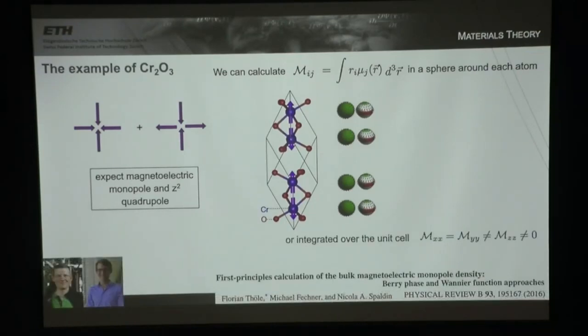We also know how to calculate, it's a bit more complicated, these quantities integrated over the unit cell. This was actually a whole PhD thesis of Florian Thöle. For those of you who work on ferroelectrics, we have all the same problems as in the modern theory of polarization for ferroelectrics, but we know how to do it. And when we do that, we find that indeed we have a Z component of this tensor and in-plane components that are non-zero. And the in-plane components are different from the Z component. So we know what magnetoelectric multipoles we have in Cr2O3.